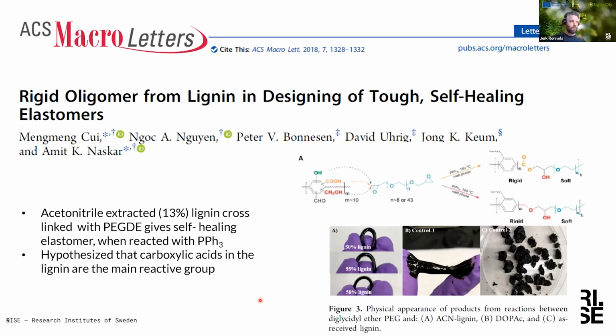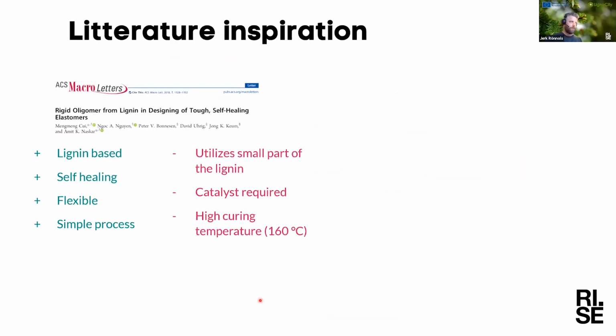So we were inspired by this. They had something lignin-based that also had the appealing quality of being self-healing. It was flexible, and they had a very simple process. They mixed the chemicals and heated it up, more or less. Some drawbacks in their method is that it only utilizes a small part of the lignin. They require the use of a catalyst in the reaction and had quite high curing temperature at 160 degrees Celsius.